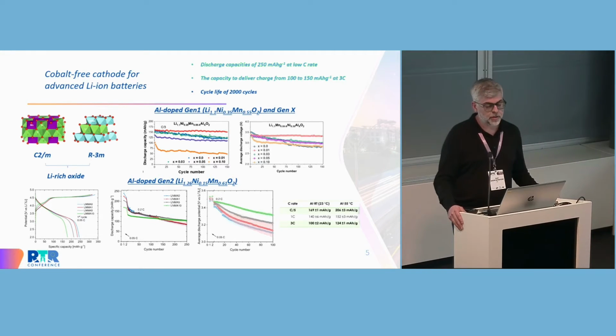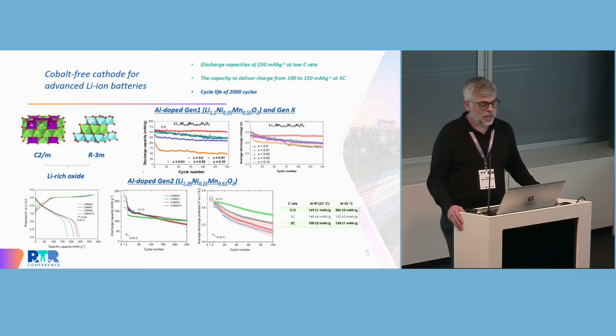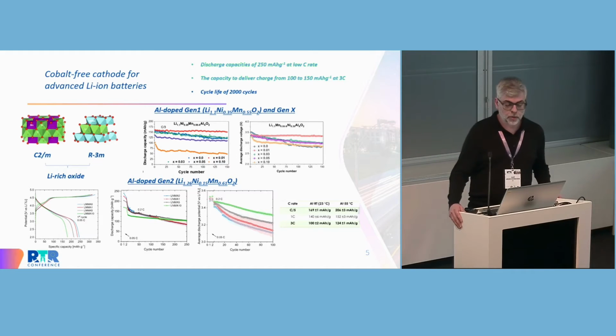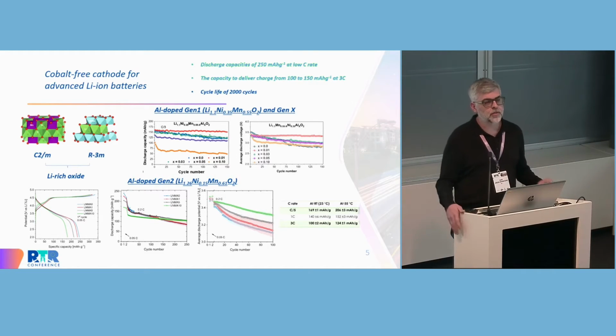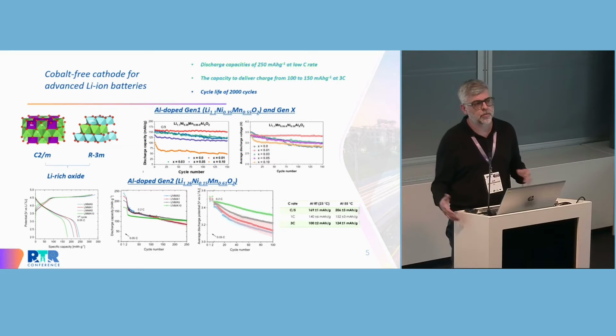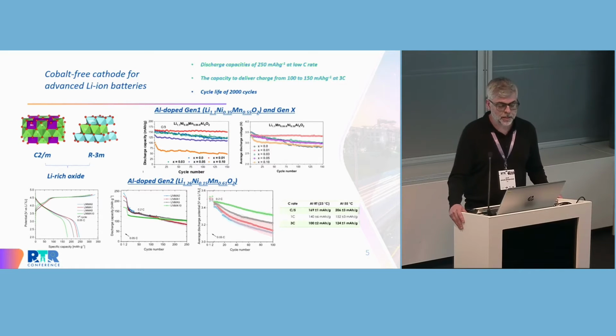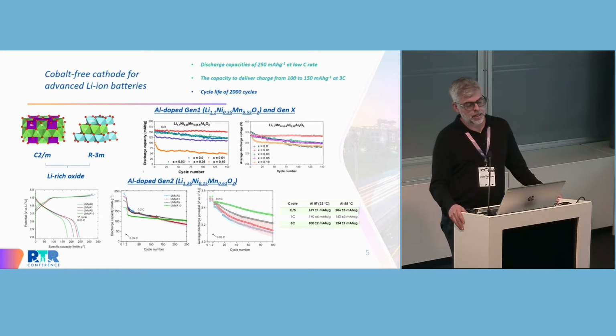In this series of figures, you can see that the parent, undoped one shows less cycling stability than the aluminum ones. We were also looking at two generations. Generation one, which is lithium nominal, and generation two, which is more lithium-rich, aiming to increase the capacity. And we managed to extend the cycle life of this parent composition and also to improve the voltage stability.